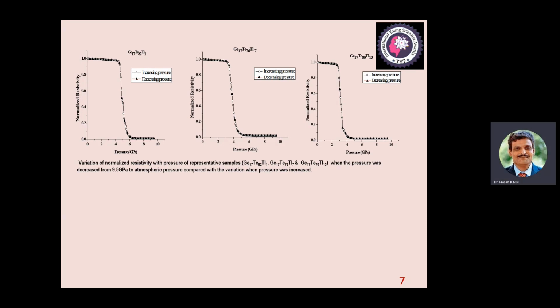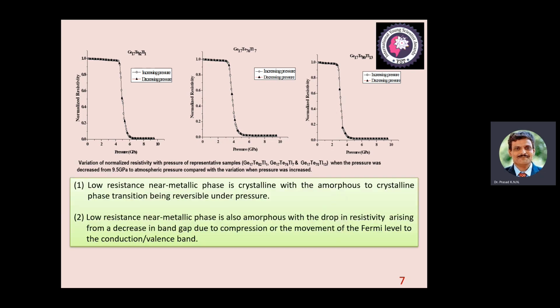And immediately we did one more thing: we tried to decompress. In the sense that we applied very high pressure from say 0 to 10 GPa, we thought of reversing it, so we did it in reverse order. When we lowered the pressure from 10 GPa gradually, we could notice that the same path was retraced. So there is a retracement of the same path, which shows the reversible characteristics.